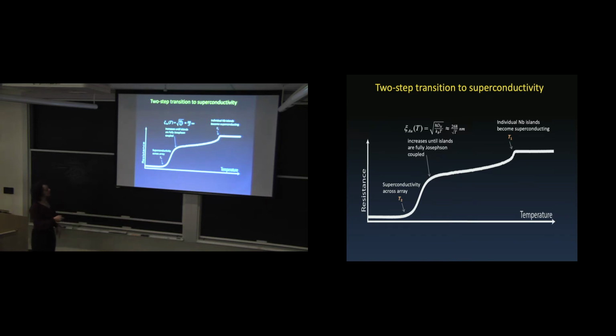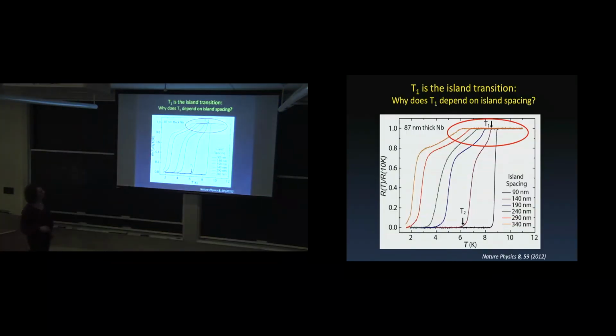But the thing to note is that this is where individual islands go superconducting, and this is where the islands are coupled. Okay? So this should depend on just the islands, and this should depend on the island spacing. Okay? But if you look at the data again, you see that the island transitions themselves depend on the spacing. And that's weird. Okay? That's something that was unexpected in this data.